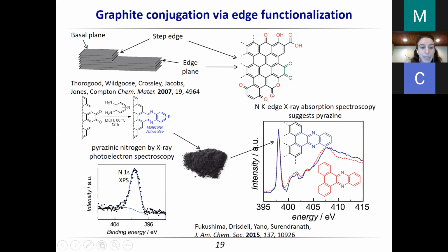Yeah, so you're right that we're only going to be able to form this pyrazinic linkage at orthoquinone sites, and also that one potential challenge would be, what if we form monoamine linkages if there's not an orthoquinone site? So we do an acid treatment to cleave all sites that are not these pyrazines. The rest of the oxygen groups are still there. They're native to the carbon. They're still there when we do this chemistry, but they don't have any signals that would show up in our CVs or other measurements.